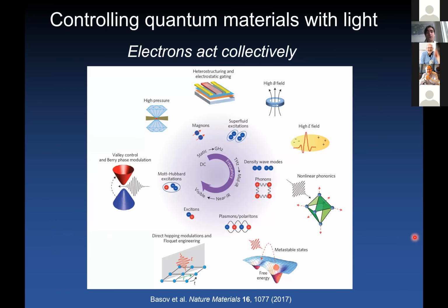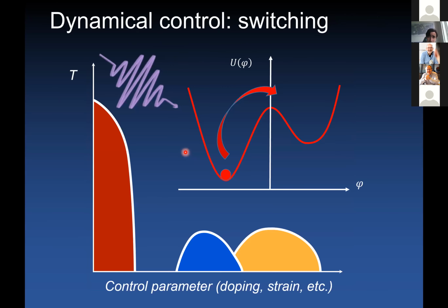The idea is that when you have systems of electrons that act collectively, then associated with this collective behavior, there are collective excitations. So in a magnetic system, you will find magnons. In a superconductor, you will find superfluid excitations, and in general, you will always find phonon modes in these crystals. And in the Mott-Hubbard systems, you will find special types of excitons. So many of these low energy modes carry an electric dipole. So it is possible to couple light directly to this type of excitation and bring the system out of equilibrium to generate states of matter that you could not access through a thermodynamic transformation. So this realizes the idea of dynamical control of materials.